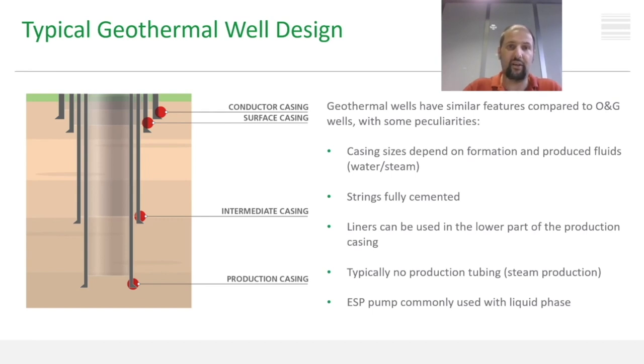But as we said, often, in order to have a high permeability, especially for high enthalpy applications, there are very big fractures in the formation, in which we can lose cement and obtain a lower than expected top of cement. Depending on the depth of the well, liners may be an option, often connected to surface with a tieback. The use of liners is given by the weight of the string and the capacity of the hoisting system of the rig. For deep wells, this is the only viable solution.